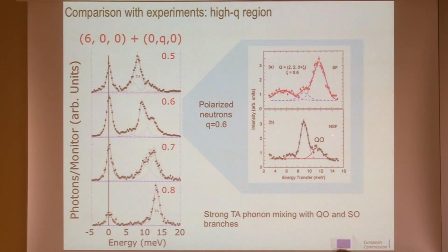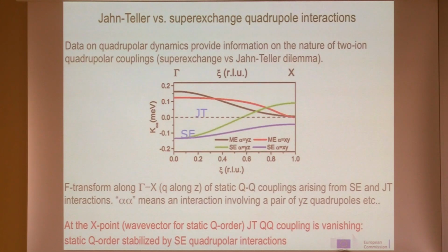This is the non-spin flip channel on the same excitation group with neutrons, non-spin flip channel, then vibration, and you see that you have a big phonon peak here with 2 wings, and these are due to the anti-crossing with the other transverse acoustic phonons with spin optical and quadrupolar optical branches that split the phonons, and you observe an excitation here and here, and you observe these ears here. And here in red, in the spin flip channel, the magnetic contribution.